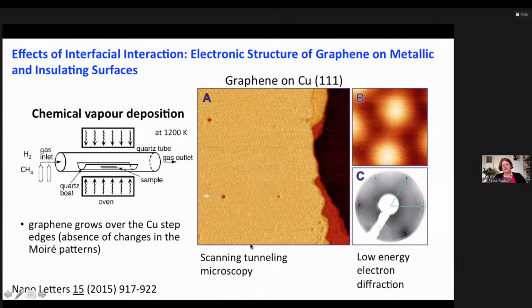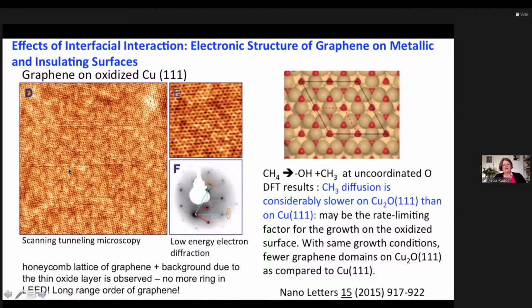The quality of the material is quite good. It has very little defects. And you can see that on the oxidized surface, you see a sort of moiré structure which comes from the oxide, which is below. And it actually turns out that on the copper oxide, you get a very good quality of graphene, because there are copper atoms on the surface that actually act equally as catalytic centers as the copper alone does. But when the methane breaks up into OH and CH3, you have a different diffusion on the oxide,